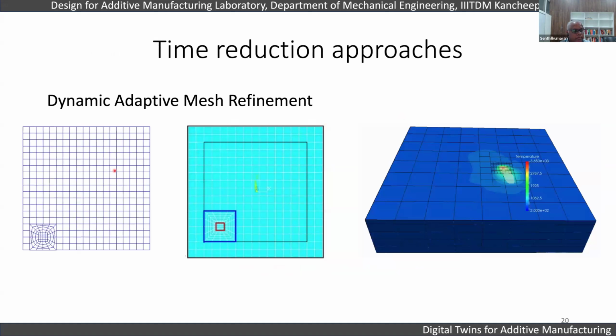For example, here, this is one of the baby steps that people have taken to reduce the time, by using a coarse and fine mesh combination, which is called dynamic mesh or dynamic adaptive mesh refinement. So you're refining the mesh in the zone of influence. You can see the mesh size is very, very fine here, a little coarser, and then much coarser in zones where the laser is not present. So like that, you can do the time reduction by reducing the computational load, by reducing the number of elements using dynamic adaptive mesh refinement.